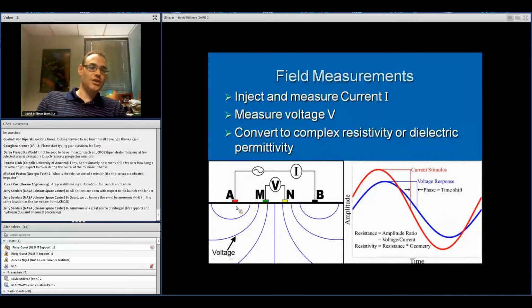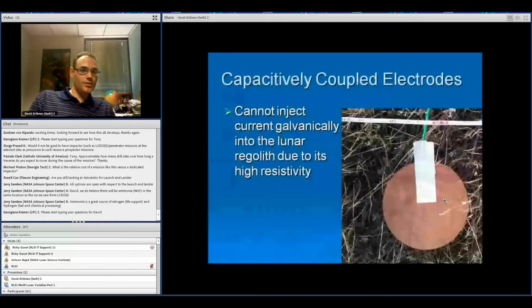This is how we do field measurements on Earth. We have two transmitting electrodes, A and B, where we inject current into the ground. We inject this with a certain frequency, make the measurement, and then sweep through a number of frequencies. We measure the voltage response with these two potential electrodes, M and N here. And then from the ratio of the amplitude response times the geometric factor, we can get resistivity. And then the time shift gives us our phase. And so that's how we make plots very similar to the lab measurements that I was showing.